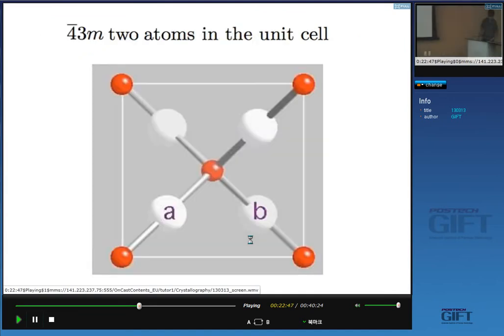Similarly, if we look at these atoms here, which are the oxygen atoms, then the symmetry elements passing through them is bar 4-3M, fourfold axis, because this is on a cube edge. So there's a fourfold axis, there's obviously a body diagonal going through it, so we've got the triad, and the mirror plane is the 110 plane, which you identified. If you look at all possible equivalent sites with that symmetry, there are only two. So there will be only two oxygen atoms in this unit cell. That is one, and that is the other. So if you locate an atom at that point group symmetry, you will only have two atoms. If you locate it at the bar 3M, you will have four. So we have four copper atoms and two oxygen atoms.